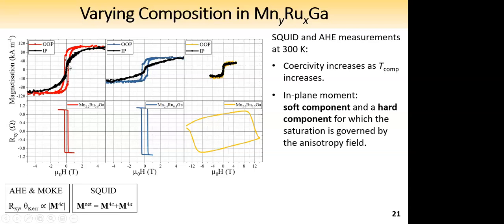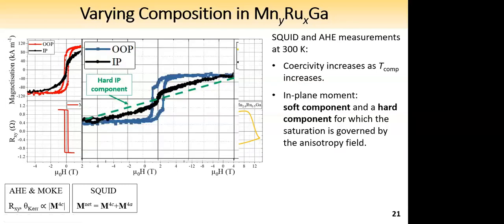However, the in-plane part has 2 different components. One of them is soft and the other one is hard. In order to understand better what is going on, I'm going to zoom into this middle SQUID loop. In an ideal world, the hard component would be simply given by the behavior of a straight line. We would start at the origin where the in-plane moment would be 0. That corresponds to the net moment being fully aligned in the Z direction. However, as the field is applied in plane, the moment would rotate and saturate fully in plane when we have reached the anisotropy field. So that explains the high field linear behavior.